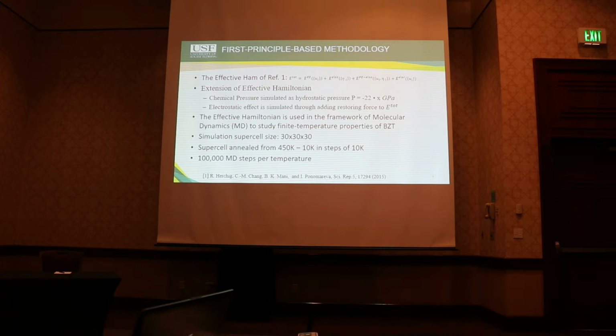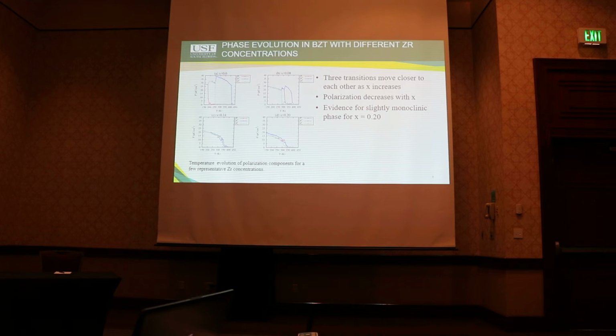A simulation supercell of 30 by 30 by 30 was used, and it was annealed from 450 Kelvin to 10 Kelvin in steps of 10 Kelvin, where at each temperature step, 100,000 MD steps were used. Here we have a couple of representatives for the dependence of polarization on temperature. For pure barium titanate, or x equal to 0, we have 3 clear phase transitions going from paraelectric cubic to ferroelectric